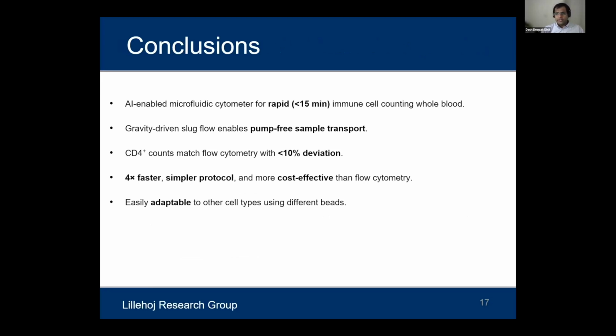So the conclusion of this study is that we built an AI-enabled microfluidic cytometer which could rapidly, in less than 15 minutes, quantify immune cells. The operation of this device is pump-free for sample transport, which totally eliminates the use of a microfluidic pump. The CD4 positive counts were compared with the gold standard flow cytometer, and we observed that in all the 8 blood samples we tested, the deviation was less than 10%. Overall, the whole protocol and device is 4x faster. The protocol is simpler because it doesn't need lysing of RBCs, and it is cost effective because it's only finger prick blood, very few microliters of blood incubated with a very small volume of beads.